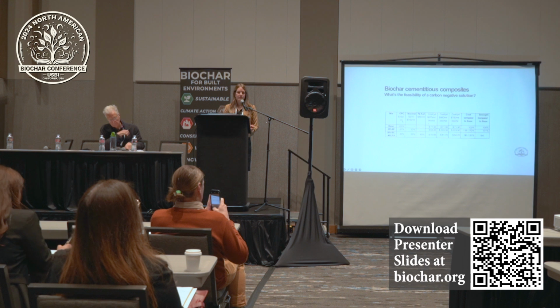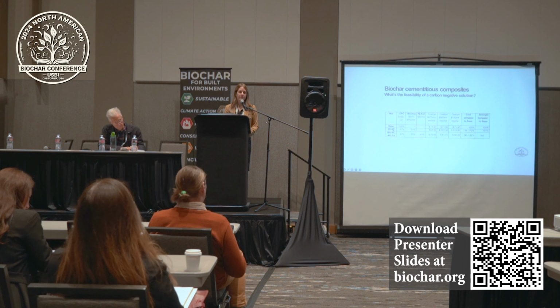And so I've put together just some estimates here on what some cost projections would look like depending on the cost of biochar. And this is where I think the concrete industry needs you all to come up with solutions where we could sell biochar for something closer to $150 per metric ton. That would get us at cost parity to cement. So if we can replace some of the cement with another material that is carbon negative and the same cost, that's going to be a pretty easy sell to a lot of people. We've demonstrated that for this carbon neutral solution, so replacing 33% of the cement with biochar, we would get a cost that's about 118 to 172% of a traditional mix, and we would have a strength that's just about the same or a little bit better.